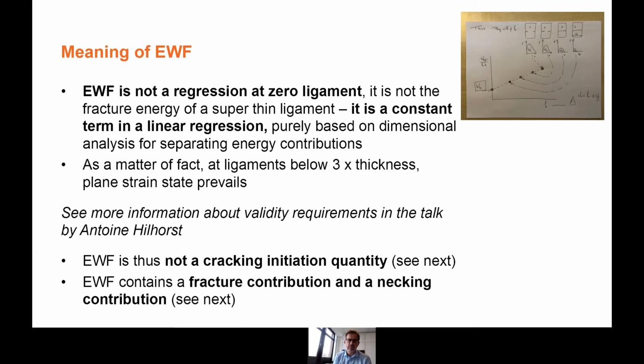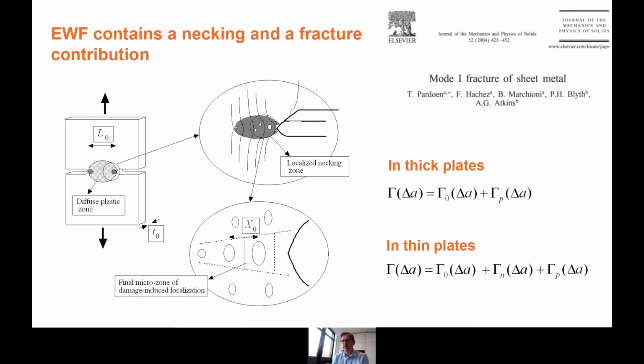It is sometimes, but in general it is not. And a lot of things can be understood by understanding that the essential work of fracture is itself a sum of two different contributions. One from an energy spent for damaging and failing of the material, and one contribution is in a work of necking at the crack tip. So let me go through that. I will start with the last point, then I will jump to the previous point and then go back to this point. But I would like to start with the big picture.